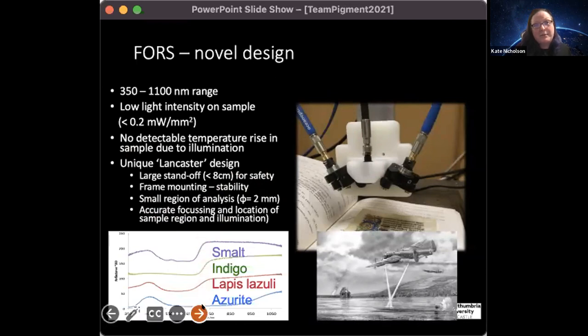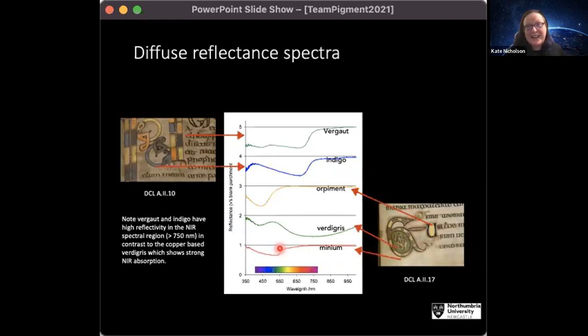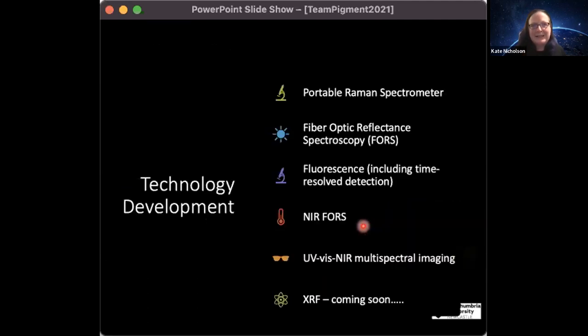You can see here a selection of blue pigments that we've analysed in the lab and the differences between them. Some of them have things in common, the step here, for example, or the absorbance down here. But some of them are different enough to see just from this part of the spectrum. And that's where we needed this technique to analyze the green in our Durham Gospels. So it's not a combination of indigo and orpiment. It is, in fact, a verdigris. So second technique required just for one pigment on the page. But wait, there's going to be more.